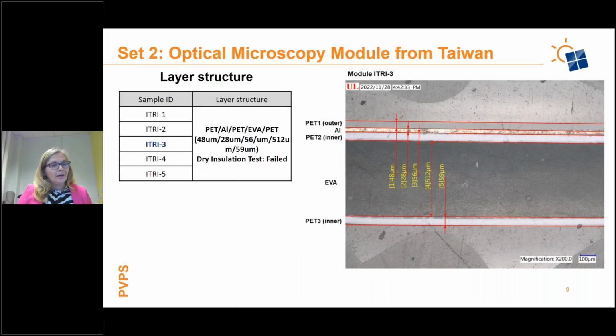We also later on got an additional set of retrieved backsheets. Interestingly enough, these are backsheets that had an aluminum layer and sheet in them. We retrieved these from Taiwan, and all of these failed a dry insulation test and had been a failed module that we looked at. And so these are microscopy images of those. These were an interesting set because these were the only modules we ever saw with this aluminum layer.